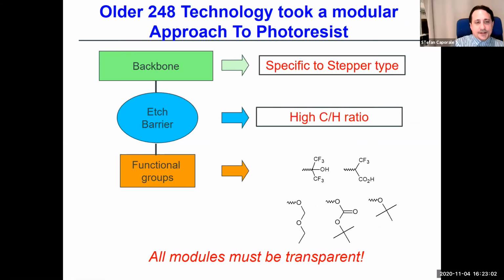So again, the backbone had to be specific to the wavelength of the light we're using. These need to be transparent. If your polymer absorbed at the wavelength of the light you're using, then your light's never going to get through your film stack, and you're never going to dissolve away at the bottom of your film, and you won't be able to do your etch and you get your contrast.